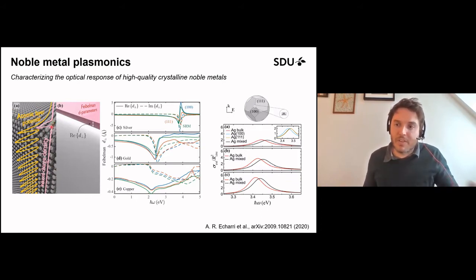functions that contain within them a lot of the information that you get out of a really heavy numerical simulation that takes into account quantum mechanical effects in the electronic band structure of the metal due to the crystallographic orientation, also including surface states that appear for certain crystal facets. They can all be contained in these simple Feibelman d-parameters, and we tabulate those once and for all, and they can be implemented in electromagnetic simulations of various metal morphologies, also in nanostructured thin films or small particles. And this helps both in theory and experiment to describe these new types of materials and capture the quantum mechanical effects that could affect their optical response.